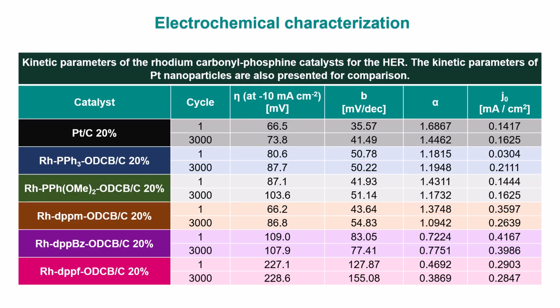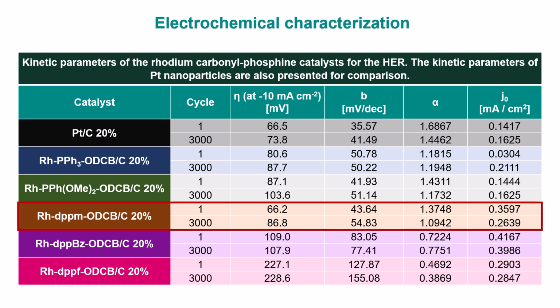The kinetic analysis revealed that the catalytic activity strongly depends on the ligand coordinated to the rhodium cluster. Among all materials, Rh-dppm-ODCB/C 20% exhibited the best overall performance, showing an initial overpotential of 66.2 millivolts at 10 milliamperes per square centimeter, which is essentially identical to commercial platinum. Even after 3,000 cycles, it maintained excellent catalytic activity, together with favorable Tafel slopes and exchange current density.